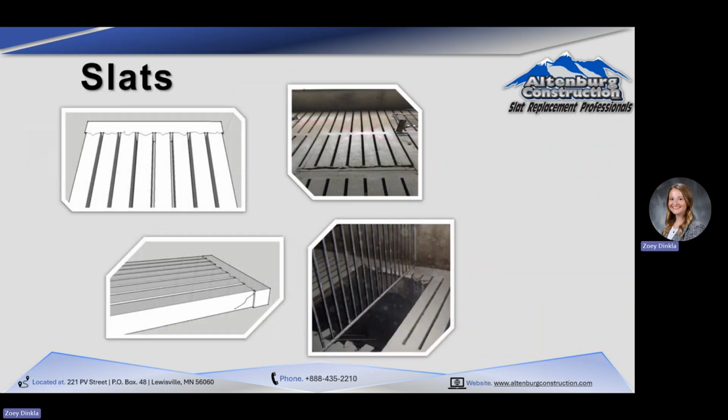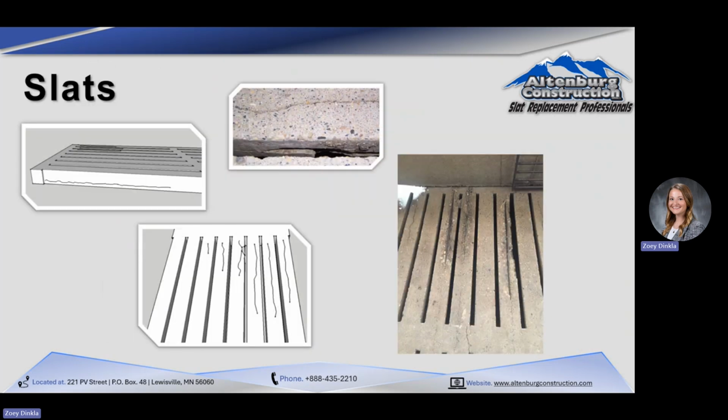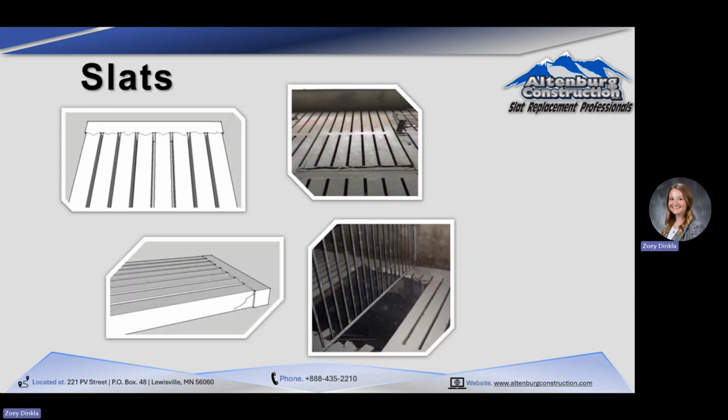The ones the engineers really get scared about, that can be a really fast failure, like these sorts of things generally happen over long periods of time. But if you get where you have a significant crack across every rail on an individual slat, that can literally just shear off. Because again, surface bearing matters. This is what's getting set on the edge of the beam. And that rebar is sitting in about an inch from the edge. So if you got poor surface bearing there and you get a crack, that's going to shear and drop.